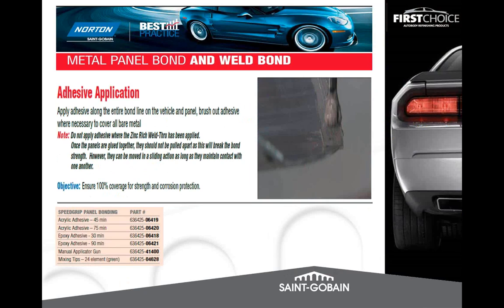So you've got a couple options there, and you can see the different cure times. So obviously 45 minutes is pretty good for doing a door skin. 75 minutes is pretty good for doing a quarter panel. 90 minutes really good for doing a big van side or roof skin. So you've got some time there depending on how big of a job that you need to metal bond or weld bond, and we'll talk about the combination of the two in a little bit here.